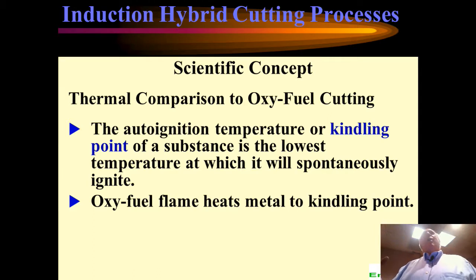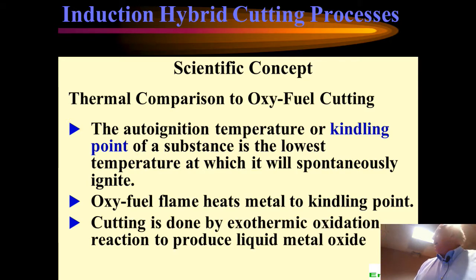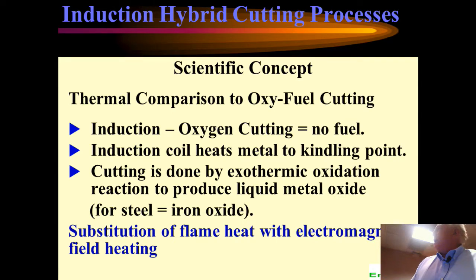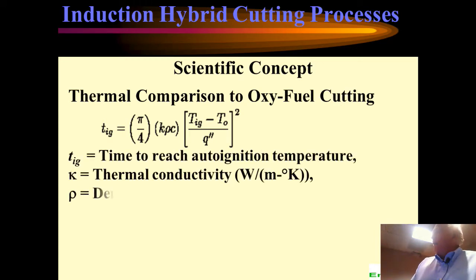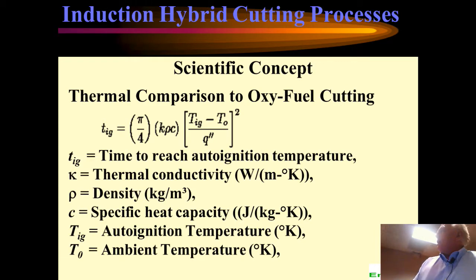So the key is how fast can you heat the surface of the material up to that 1600 degrees. So we started looking at essentially induction oxygen cutting, and if you look at it, there's really no fuel any longer. The induction coil is doing the heating, and along with the oxygen, we're doing the cutting. And this is basically the equation that covers it.